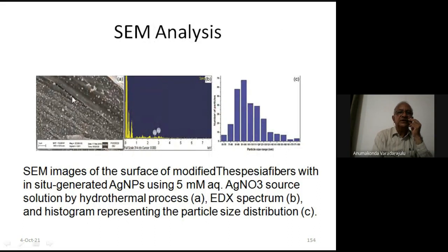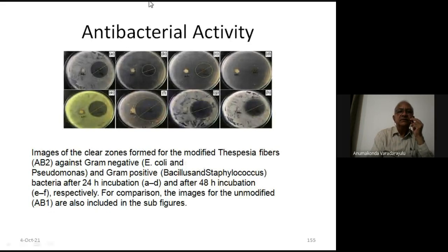So how to prove? These are the nanoparticles, silver nanoparticles, spherical nanoparticles generated inside the fiber. EDX spectra indicated the presence of the silver metal in nano form. This is a particle size distribution. It showed very good antibacterial activity after 24 hours incubation, after 48 hours incubation. This is against E. coli, Pseudomonas, Bacillus and Staphylococcus, etc. So against both the gram negative and gram positive bacteria, they showed excellent antibacterial activity. And after 48 hours, the antibacterial activity increased.